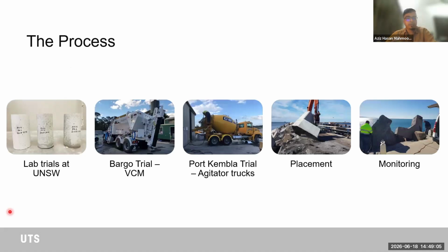So the process involves the typical stages of any concrete supply or any next generation or new type of concrete supply. The lab trials were undertaken at UNSW as part of the project, and we did a trial with a volumetric concrete mixer at Bargo, which didn't go quite so well because these volumetric concrete mixers allow about 10 to 15 seconds of mixing time, and with geopolymer concrete, that's not enough time to mix all the components into the concrete mix. Then we went for another trial where we used agitator trucks, and it did really well, that trial. And I'll take you through a bit more information with the trial.